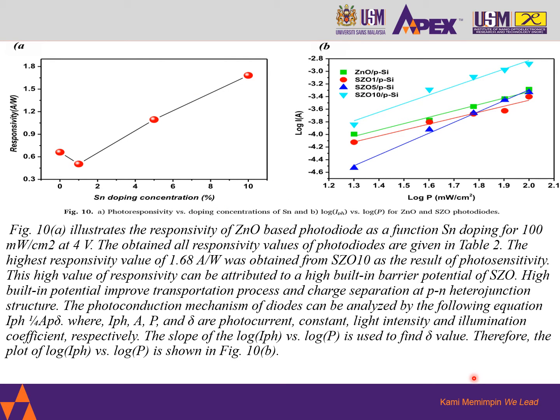Figure 10a illustrates the responsivity of zinc oxide based photodiodes as a function of tin doping for 100 milliwatt per centimeter square at 4 volt. The obtained responsivity values of the photodiodes are given in table 2 that we have seen earlier. The highest responsivity value of 1.68 was obtained from SZO10 as the result of photosensitivity. This high value of responsivity can be attributed to a high built-in barrier potential of SZO. High built-in potential improves the transportation process and charge separation in the p-n heterojunction structure.